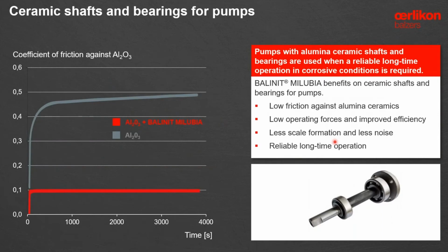Okay, ceramic shafts and bearings for pumps. Here again on the left, you can see the behavior on the pin on disc test of just a bare uncoated aluminum oxide as compared to coated with BALINIT MILUBIA. Minimal increase in friction as the system runs in, and they're very constant friction coefficient.